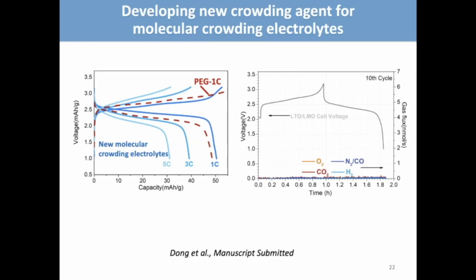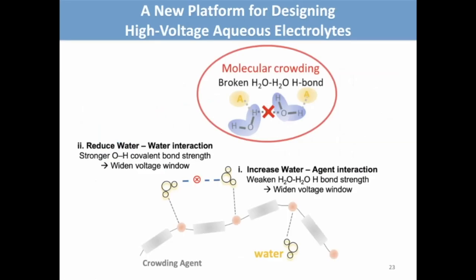So here you can see that with the new crowding agents in blue, we can significantly reduce the overpotential in the cell compared to the PEG molecular crowding electrolyte. And using spectroscopy, we can also show that there is no sign of hydrogen evolution or oxygen evolution in this new type of crowding agent electrolyte.